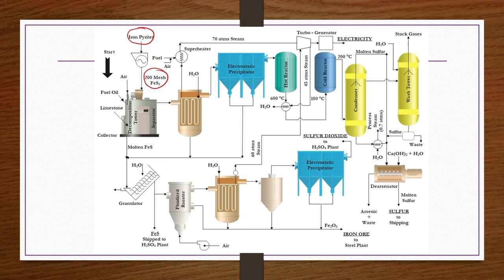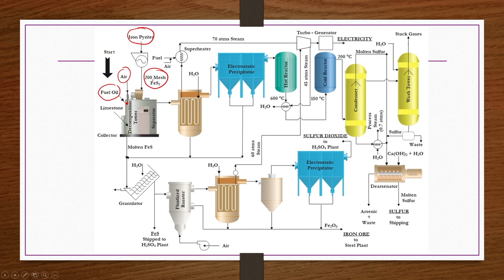There is a smelter furnace in which different operations take place. At the top of the smelter, oil burners are supplied with fuel oil and air. Combustion gases from oil burning are useful for FeS2 thermal dissociation. Size-reduced FeS2 is introduced into the smelter, thermal dissociation occurs at about 1300°C, and gases plus FeS liquid droplets are released.